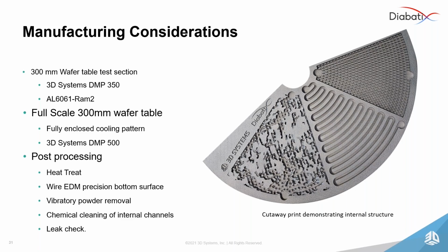And from a post-processing perspective, heat treat was applied to this. We have various heat treat options we have experience with across our material portfolio. And this was set up completely flat on the build plate, so a wire EDM process will create a precision flat bottom surface. And in this case, we used simple vibratory powder removal. In the fully enclosed use case, where we're actually practically applying this, we would use chemical etching or chemical cleaning to clean out those interior channels. And we've shown practical results of almost zero particulates, in many cases zero particulates, through the chemical cleaning process. Across our material portfolio, we have slightly different techniques to clean the interior channels to ensure that we adhere to high cleanliness requirements of the clean rooms for semiconductor foundries.